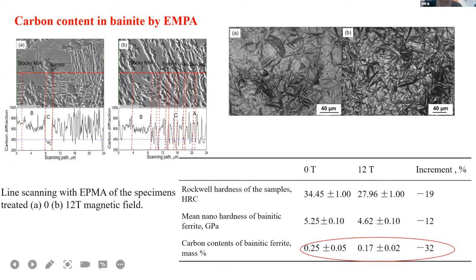The other phenomenon is about the carbon content in bainite by EPMA. We found that the carbon content in bainitic ferrite under the magnetic field decreases. So it means that the magnetic field decreases the carbon content in bainite.